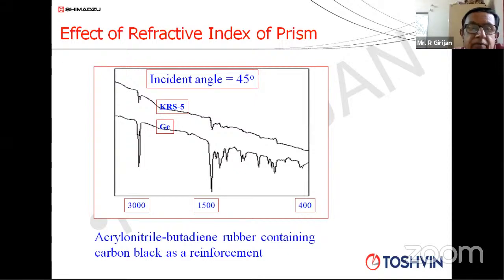This is a spectrum of acrylonitrile butadiene rubber containing carbon black as a reinforcement material. We recorded the spectrum using a KRS5 window crystal. That is what is at the top. You see, it's a very bad quality spectrum. No peaks are seen. But we used the germanium prism and got a good quality spectrum, because germanium is the only crystal having a refractive index more than carbon black. Germanium's refractive index, I suppose, is more than 4, definitely more than carbon black.